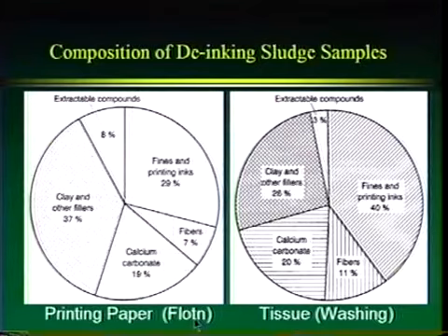Okay, now let's compare that with all those plastics and metals and wood in the rejects. Now let's look at the de-inking sludges. What we'll see in the de-inking sludges is they're much smaller particles and more fines and fillers and clays and things like that. So if we look at this one right here, which was making a printing paper, and we're going to use a flotation process, what we're getting rid of is a lot of clay, a lot of fines and printing inks. Here's fibers at 7%, and here's calcium carbonate at 19%.